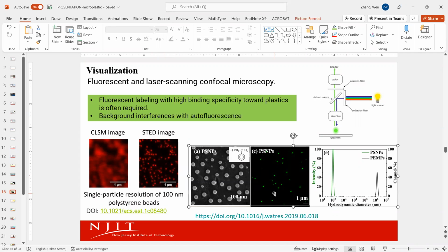We use a commercial plastic particle, a polystyrene particle. They're made with a fluorescent dye inside their particles, not outside, not the surface coating, but inside. So when we perform this study, we are not really worried about the contamination or the coating detachment during the experiments.